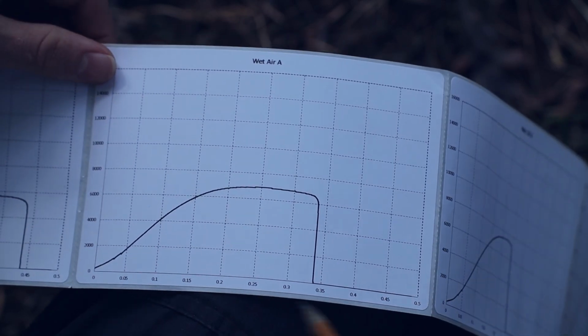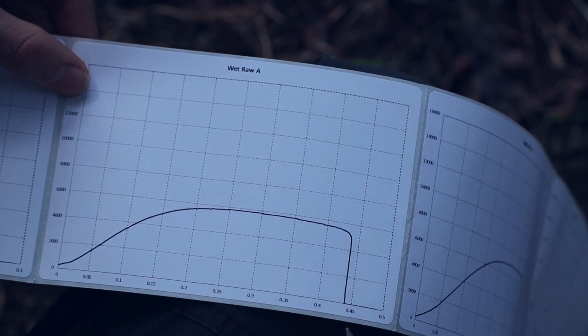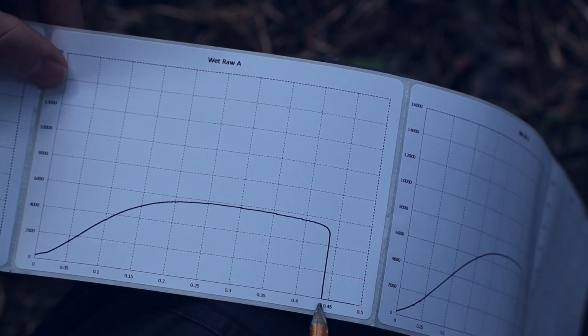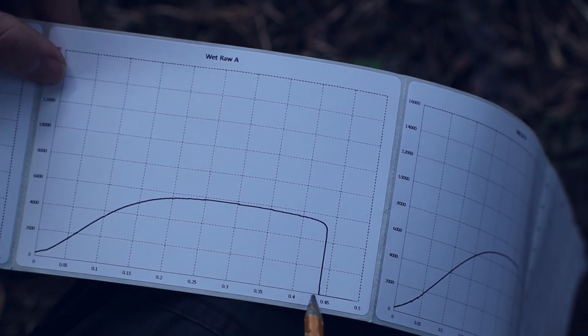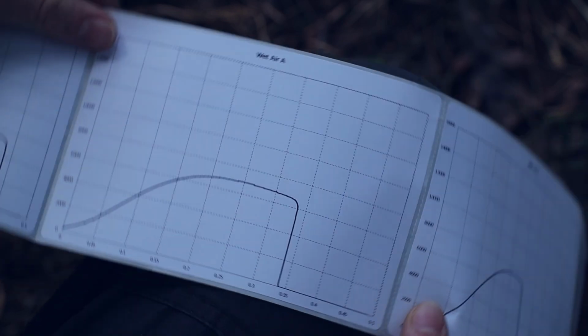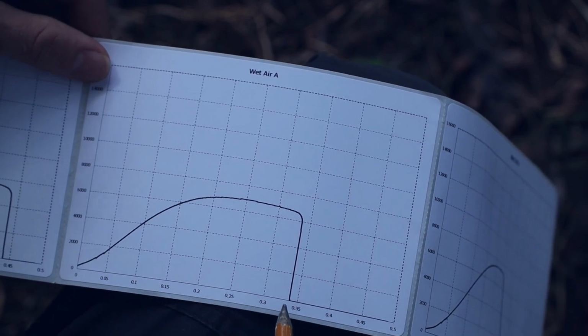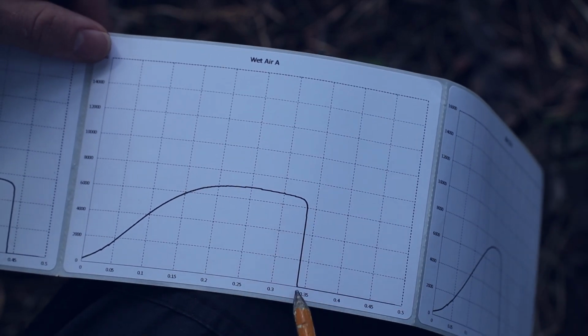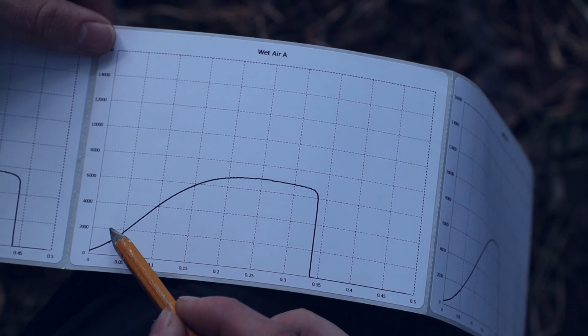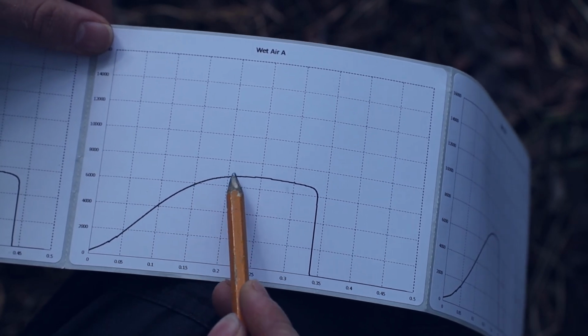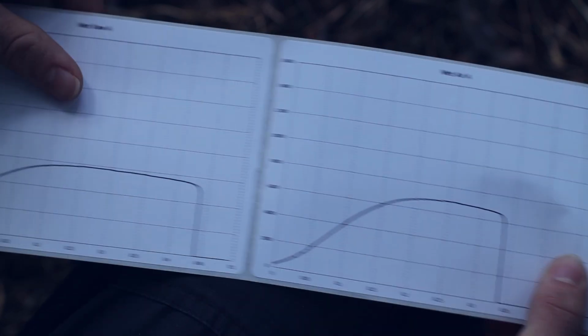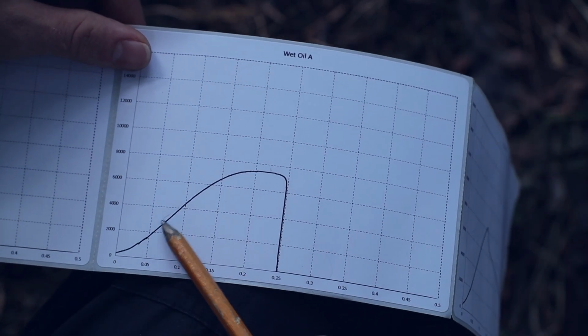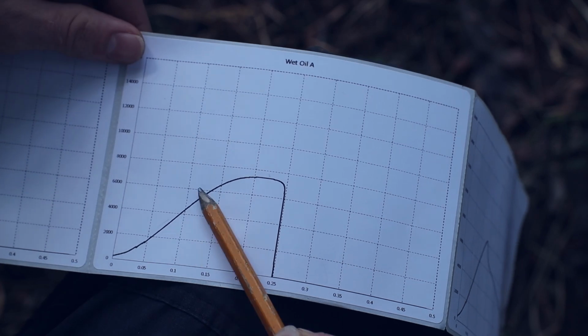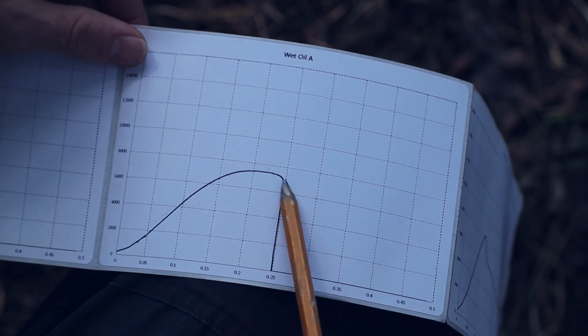So with glass fibers, it makes it a little bit stiffer and you lose some of that necking at the end. Air annealed sample, we already see a significant increase. Unannealed sample right here almost went to 0.45 on the strain scale. The annealed sample went to below 0.35. It broke off sooner, and you can see that the slope right here is stiffer and our ultimate tensile strength is higher than it was over here. That trend continues with the oil annealed nylon. We are significantly steeper here, and that makes it stiffer, less plastic deformation, and it's breaking off sooner.